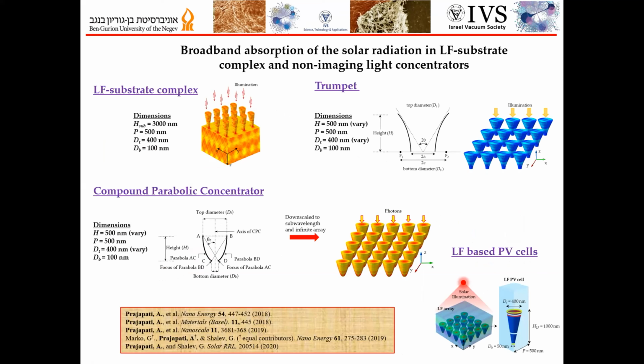Based on this motivation, my co-workers and I have studied the light trapping mechanism in light funnel substrate complexes, in trumpet or hyperboloid, in ellipsoid, in compound parabolic concentrators, and in light funnel based PV cells in detail, and shown a significant broadband absorption efficiency enhancement that leads to higher power conversion efficiencies. The broadband absorption efficiency is the absorptivity averaged and weighted with the standard air mass 1.5 global solar spectrum. For more details of this work, please go through the references below, which are published in various journals.